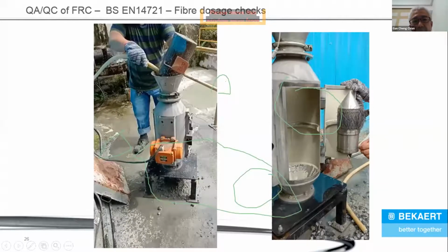So what happens is that you pour wet fiber concrete into this machine, and what comes out of it is the aggregates, sand and cement. But where are the fibers? The fibers are here on the right hand side. They are stuck to the magnet inside this machine. With this magnet, you can collect your fibers, weigh them, and within 10 or 15 minutes, you can already do your fiber dosage check. So this speeds up the checking of the fiber dosage very fast, and as a result, we do this type of check every day.